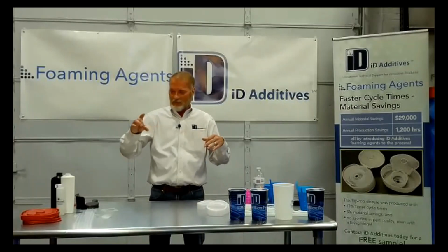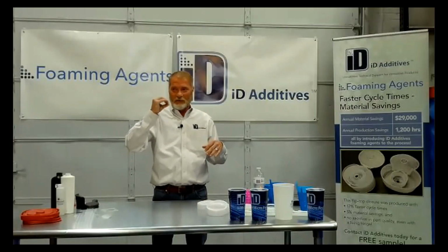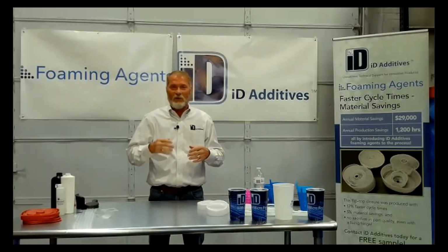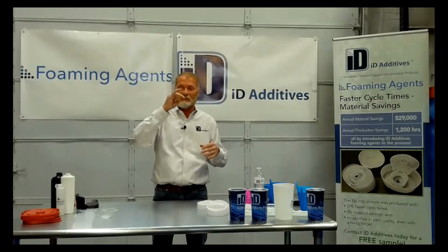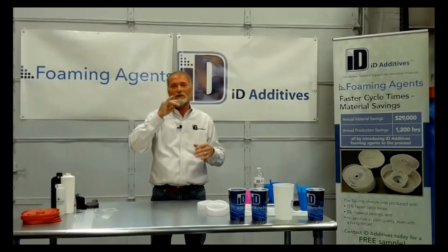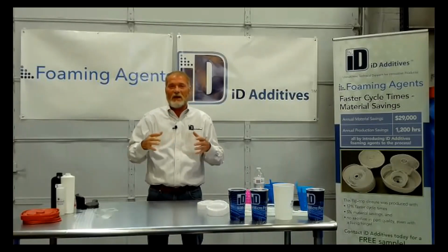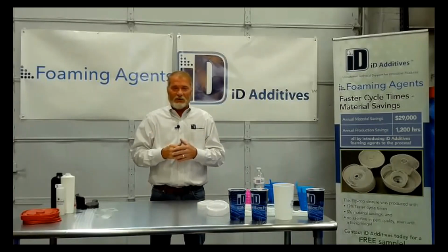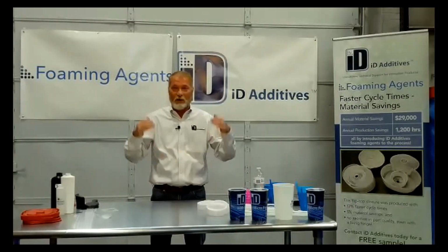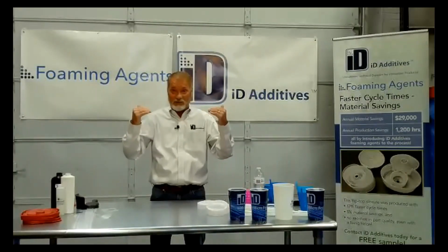If you got a void like so, or even like so, and you add that chemical foam, now that void turns into a tiny little void because the foaming agent's expanding in those voids. So if you use too much nitrogen when you're adding chemical foam, the nitrogen will overpower it. So you want a nice balance between the two.